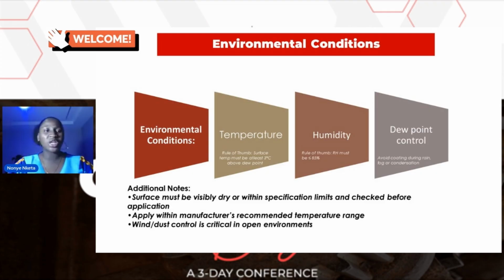So as much as you want to see your job done fast, as much as you want to meet up to deadlines, please, you have to be very, very careful, because these assets are very critical and important, especially in the oil and gas environment. In fact, every environment actually, because we have steels performing different functions in different industries. Then the humidity, as a rule of thumb, relative humidity must be less than or equal to 85%. Then dew point control too. Avoid coating during rain.